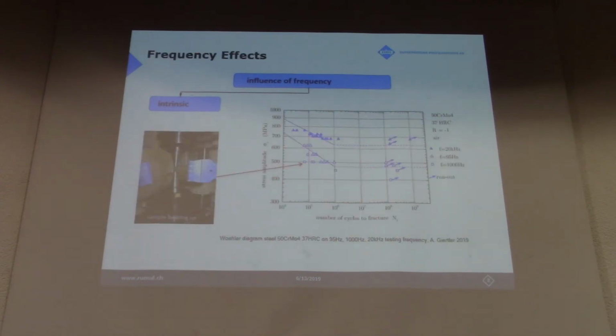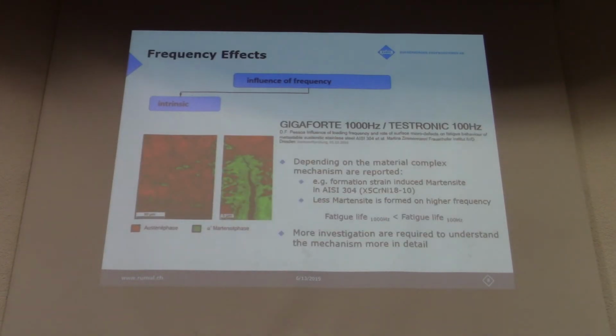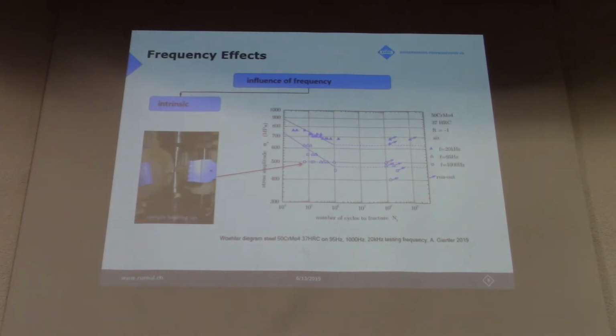Here we could do an investigation together with the Technical University of Osnabrück. We could do some tests at Rumul at 1000 Hertz testing frequency, and at Osnabrück they did tests at 20,000 Hertz testing frequency and at around 100 Hertz testing frequency with, I would say, a conventional resonance testing machine for Baru.